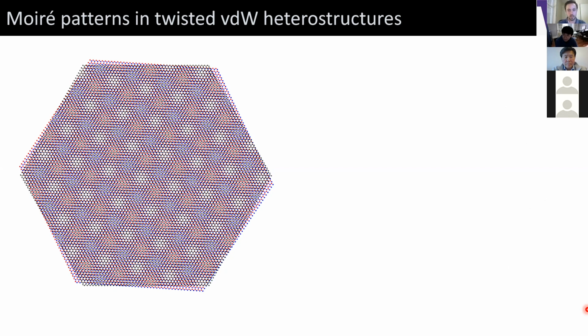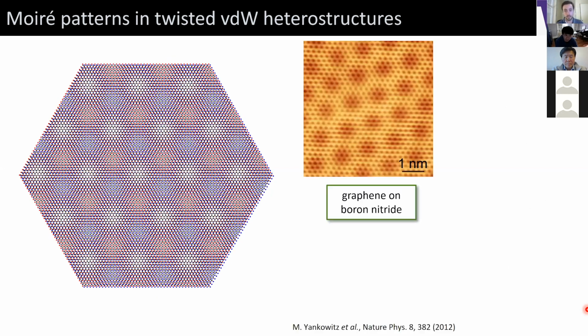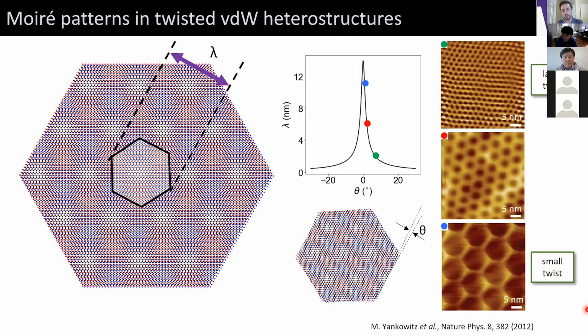And as Leo mentioned, some of the STM work I did about 8 years ago now helped to highlight that these Moiré patterns are really quite important in modifying the material's properties. So here's an STM image of graphene and boron nitride, and you can see a small hexagonal lattice highlighted in white, arising due to hexagonally bonded carbon atoms in the graphene lattice. And then on top of that, there's a larger hexagonal superstructure, which is this Moiré interference pattern between the two crystals. And we can make different samples with different twist angles, and this Moiré pattern goes from large to small as we tune the twist angle from small to large. And this follows a simple geometric dispersion, so basically everything works as the geometry should dictate.